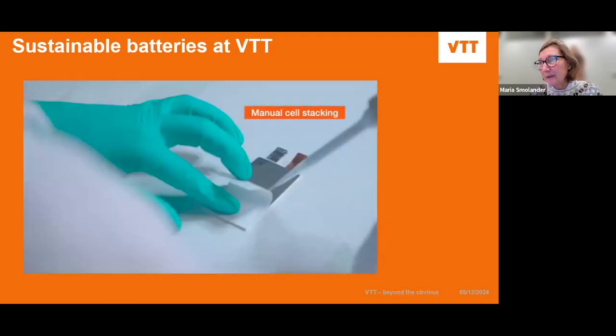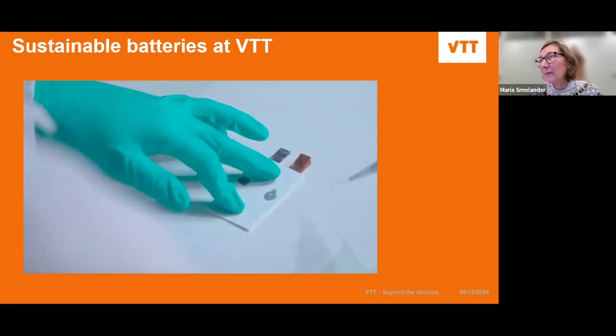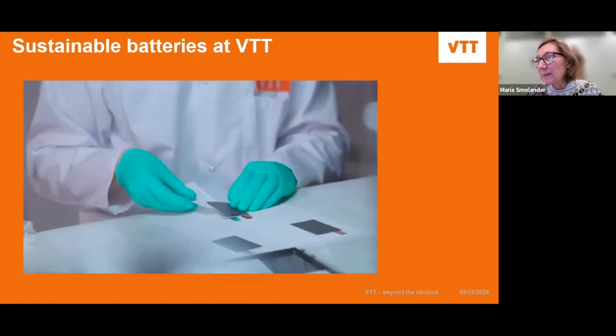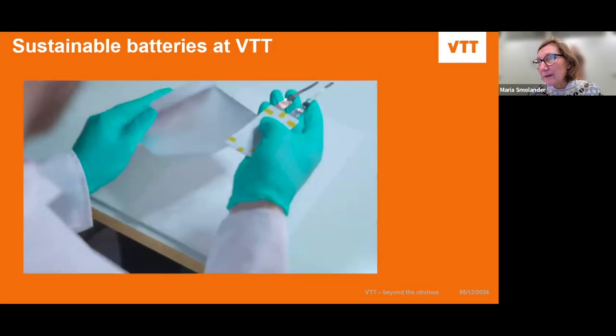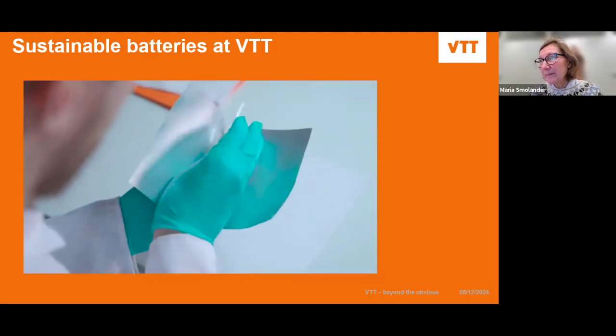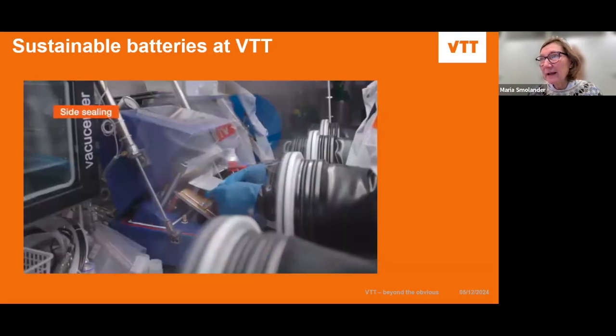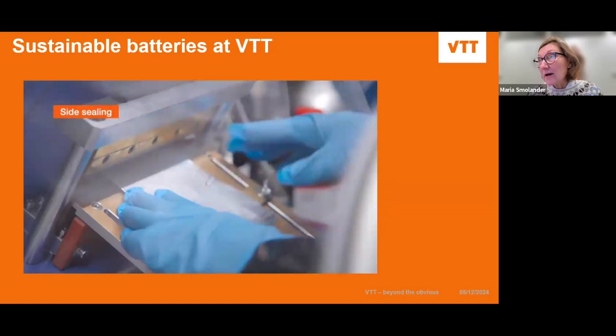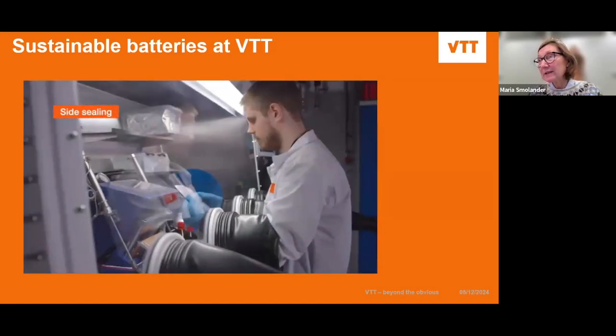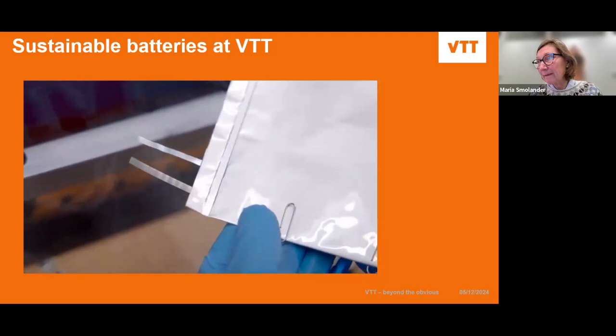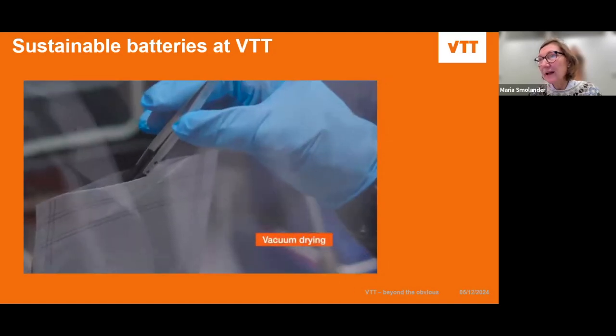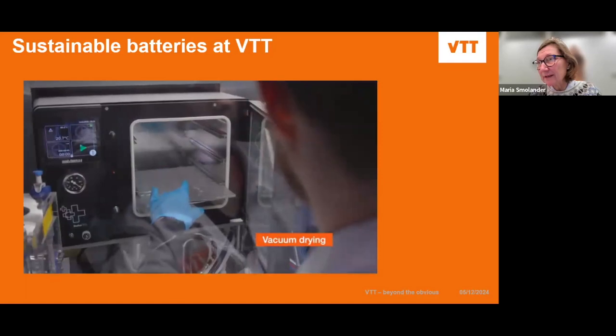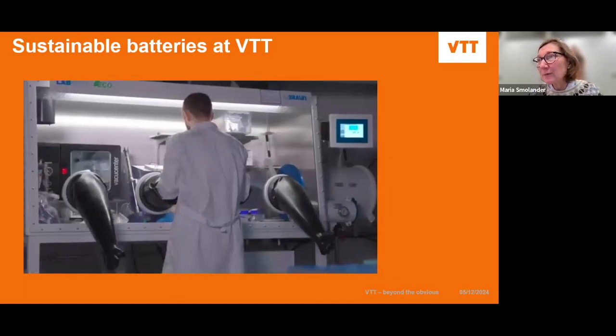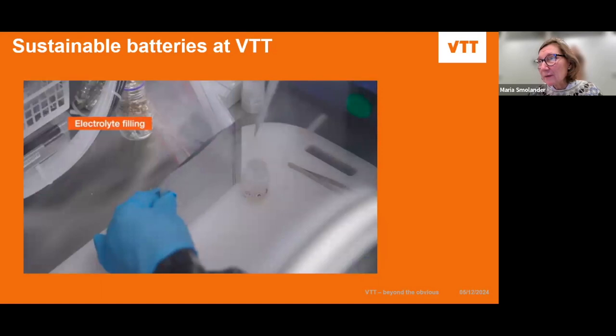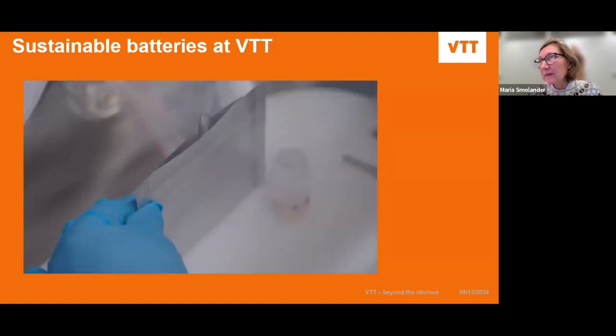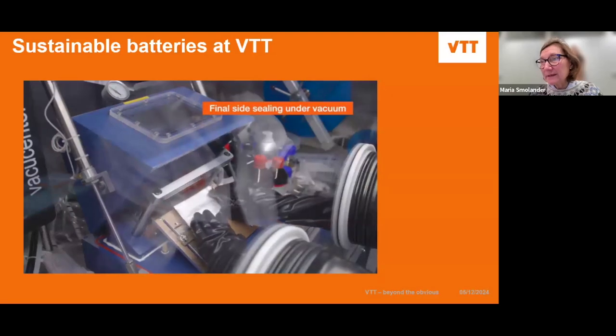And this can be done in the normal atmosphere, of course, depending a little bit on the chemistry. But then it is put into this encapsulation material and taken to the oxygen-free argon glove box, where it is sealed and then dried, and the electrolyte is filled in. Okay, now it's vacuumed a little bit. Electrolyte goes in, and then it is sealed.